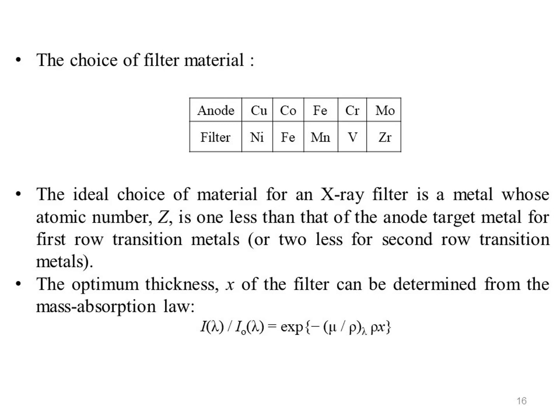The optimum thickness of the filter can be determined from the mass absorption law, which is I lambda over I naught lambda is equal to exp minus mu over rho lambda rho x, where mu over rho is the mass absorption coefficient at the wavelength lambda, rho is the density of the material, which for nickel metal is 8.92 gram per centimeter cubed, and I lambda and I naught lambda are the transmitted and incident X-ray intensities respectively.